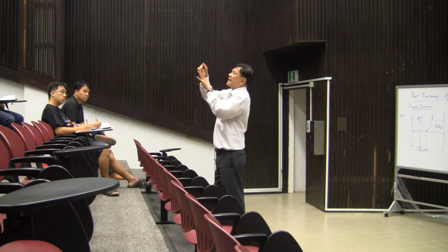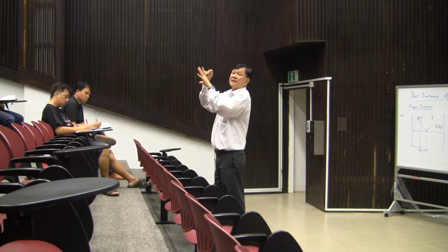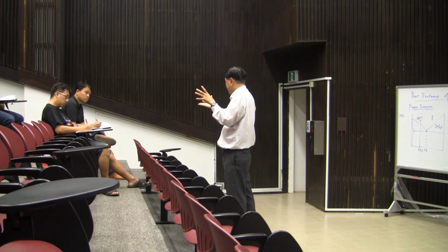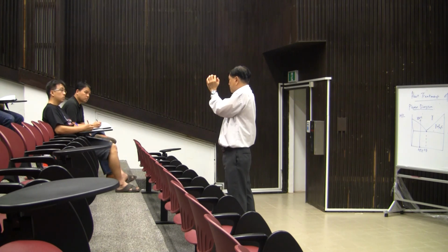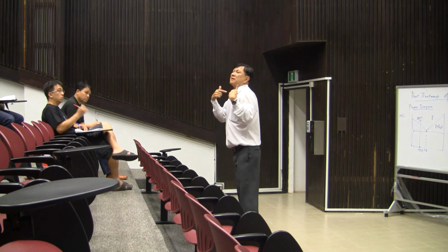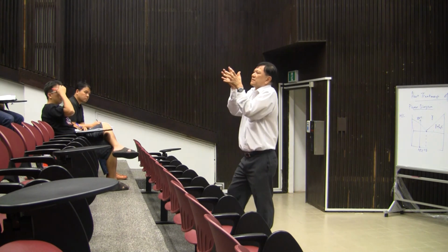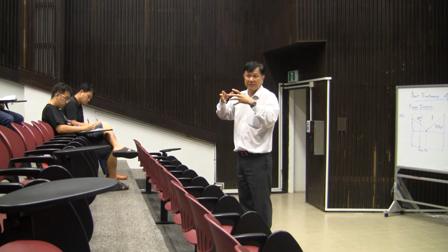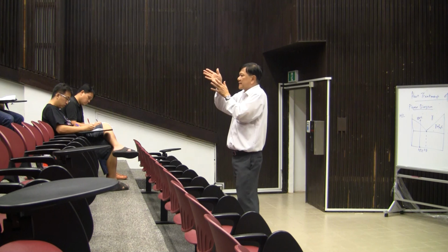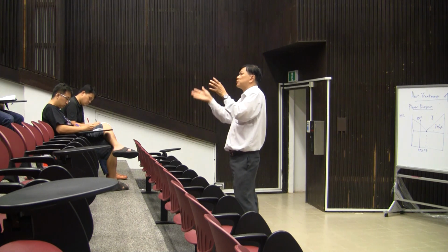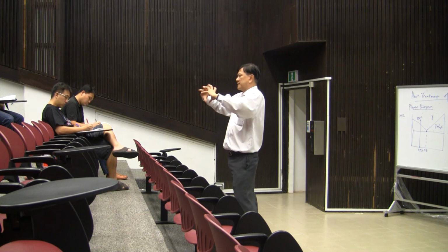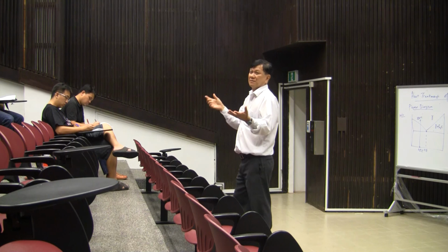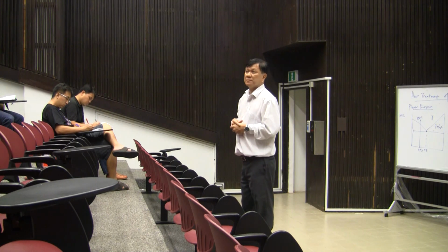So if my steel has got retained austenite in it, when this austenite changes to martensite, my volume will increase. So I will not have what? Dimensional stability. That means my dimension is unstable. Retained austenite can anytime change to martensite. When it changes, my dimension will be affected. So if you talk about precision, that will be a problem.